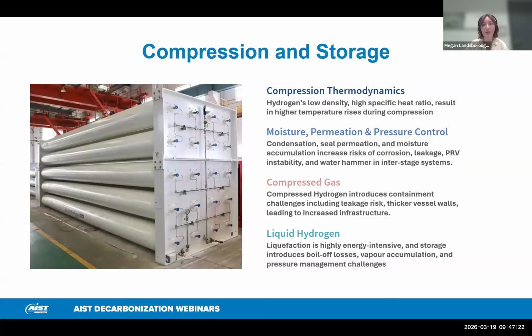Now, if we want to take a look into storage, first, if we focus on the pressurized vessels, the higher the compressed gas, the higher the energy state the hydrogen is held in, which is typically an advantage. However, higher pressure gas always comes with risks. Higher pressure also leads to an increase in wall reinforcements to support the pressure. And with the increase in wall thickness, the vessel becomes heavier with a smaller volume, requiring more vessels and in turn more infrastructure.